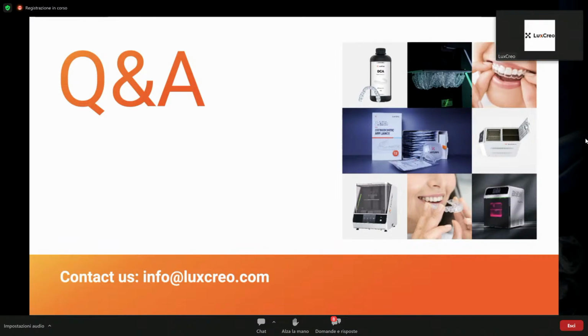Good idea. Quite a few questions around, can you use this resin with any other printers on the market? Yeah, the industry is not ready for that yet. From our point of view, our resin is higher viscosity, higher molecular weight, which means that's how you get the high performance. Luxcreo has mastered the high viscosity printing, consistently batch to batch, across the batch, machine to machine. We have many hundreds of printers printing for footwear as well as in dental. So you have to have consistency.